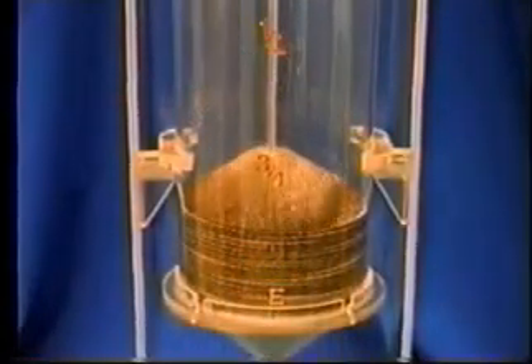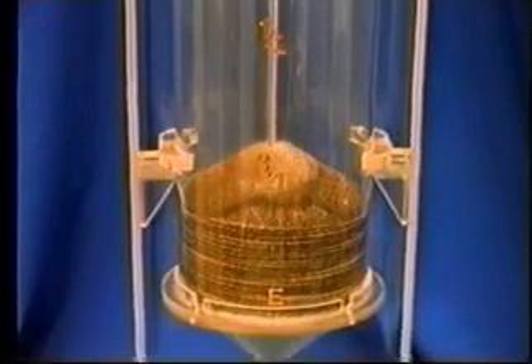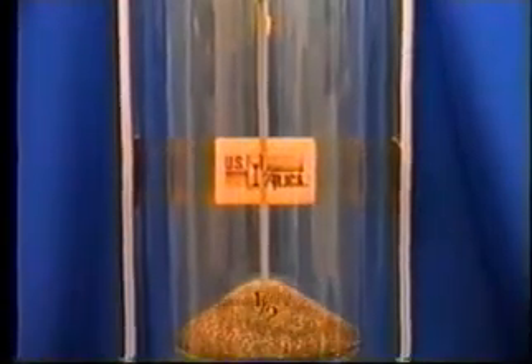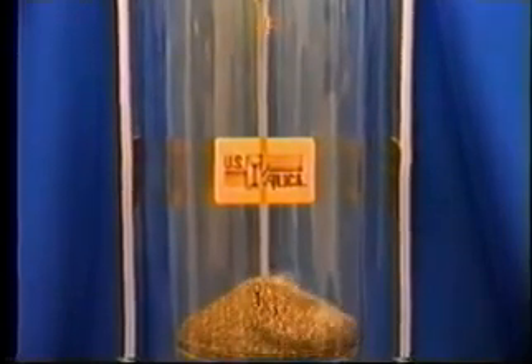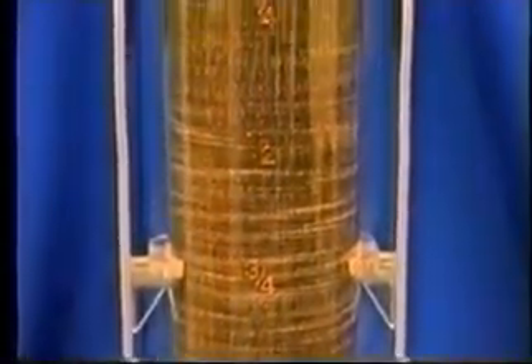Again, the sand segregates immediately within the bin, the fine staying in the middle while the coarse rolls to the outside. The outside of the bin shows almost all black material or coarse sand, although only 40% of the total sand is black. This drawing illustrates what occurs within the bin. The center core, depicted by red, is a concentration of the finer screens. The pink area contains a blend of coarse, fine, and intermediate grains, and the white area contains the coarser grains.